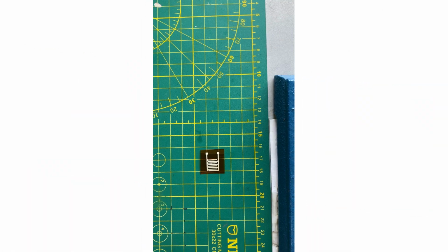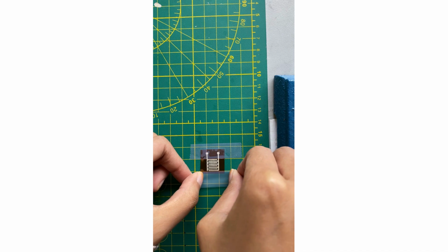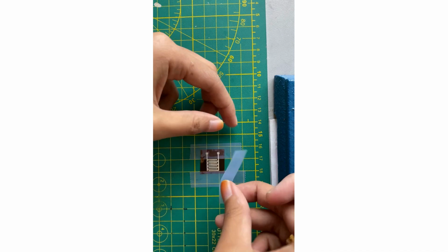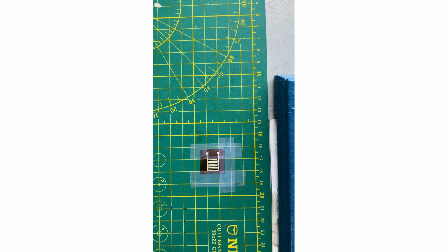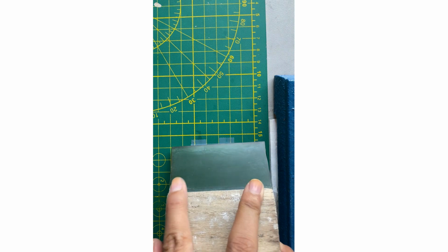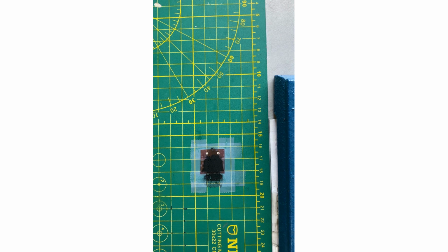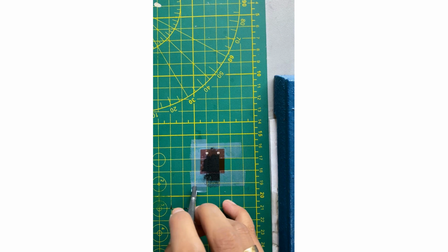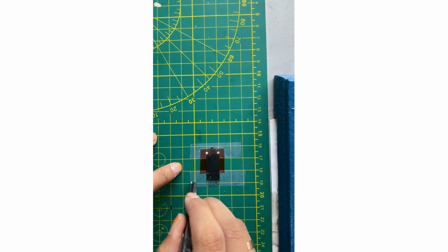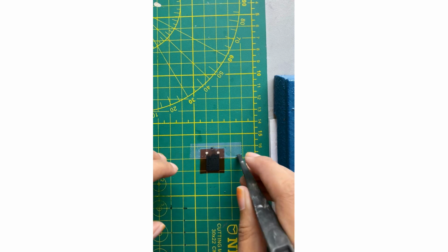For the second layer, the sensing material paste that has been prepared was coated onto the printed electrode using the Doctor Blade technique. This technique is done by pressing an amount of graphene paste, then depositing it on the sensor surface and spreading it to provide a homogeneous sensitivity layer at 1 cm square. The area on which the material was deposited was controlled by developing a 1 cm square area using scotch tape. The squeegee was placed over the substrate at a consistent velocity with a specific contact angle and height in this process. The movement of the squeegee uniformly distributes the paste onto the substrate, resulting in a thick film gas sensor. Lastly, the sample was annealed at 150 Celsius for 30 minutes in the oven.